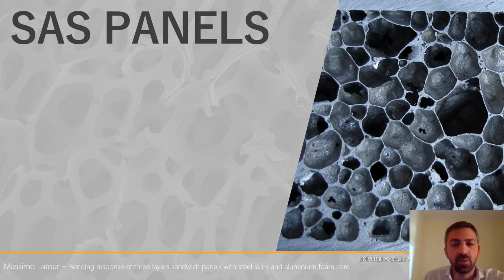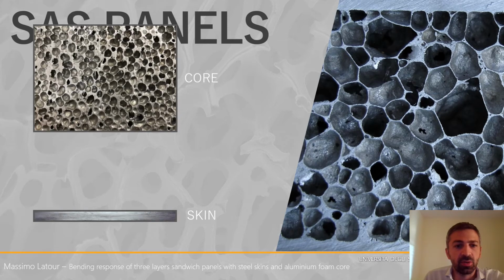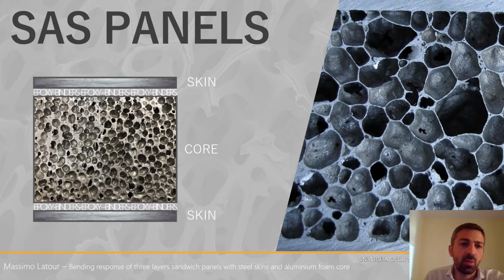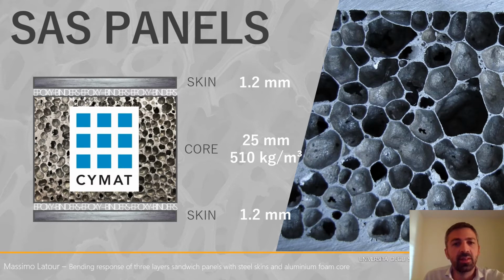So the idea of this work is to study a proposal which is already existing, which is the use of steel-aluminum foam-steel panels, where the internal core of the structure is composed by an aluminum foam core, while the external skins are made of steel. The elements in our work are joined by means of glue, of epoxy binders. We have studied in this preliminary work the behavior of a sandwich panel, which is composed by a core of aluminum foam of 25 millimeters thickness with a density of 510 kilogram per cubic meter. The skins are made of carbon steel. They have a thickness of 1.2 millimeters. The aluminum foam that we have used was provided by Cymat Ltd, Canada.